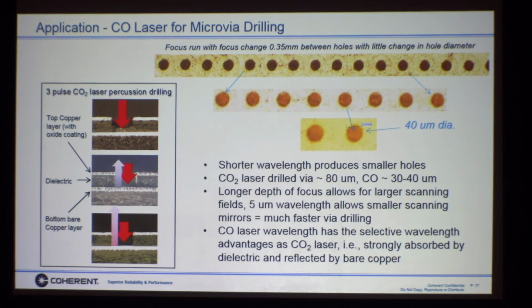The next application that's near and dear to our heart anyway is via drilling, okay? The majority of laser microvia drilling done today is done with CO2 lasers. And again, I mentioned before, CO2 lasers are diffraction limited to 55 microns and practically limited today to around 70 or 80 microns, okay? If you want to drill at an acceptable speed. So 70 to 80 microns are the holes that are being drilled today. Here we demonstrate holes that are drilled with the CO laser at 40 microns, okay?